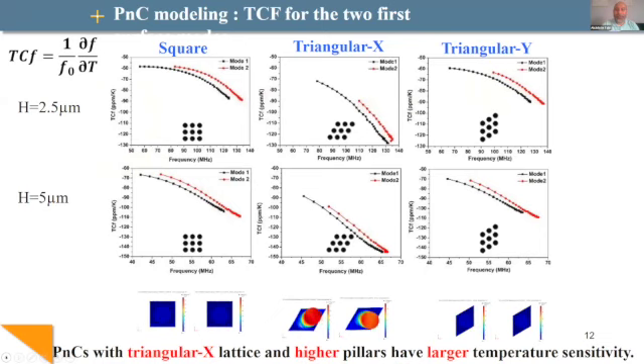No, without equations. Generally we see that the wave is localized inside the pillars. This is the same for all the configurations, square and triangular, both X and Y. But if I answer directly, if you consider, for example, Rayleigh waves and shear waves, Love waves, they don't have the same sensitivity. They are both surface waves, and the difference between Rayleigh and shear waves is the polarization of the wave. In this case, it's exactly the same. In the case of triangular X, the polarization of the mode is not the same as in the Y direction. And this explains very simply the difference.